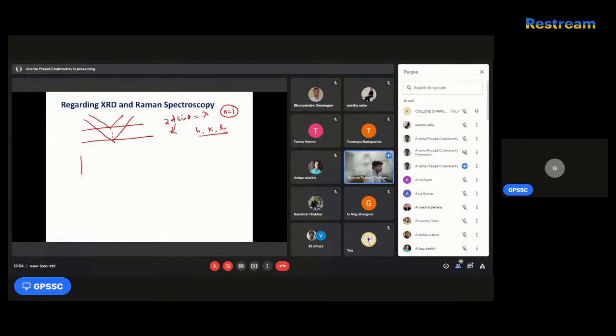So from that you can understand the different crystallographic structures through this XRD, X-ray diffraction, at different 2 theta angles. Generally you have to plot 2 theta with respect to intensity, and you have to take this intensity as arbitrary, because intensity can vary with respect to the machine, but the peak position is specified. So you can see different peaks are coming, and you have to analyze with different software, like the Rietveld analysis, as Marpanda sir has already told. Then you can go for the published XRD files through JCPDS, in the journals. Then you can confirm whether the material you are fabricating already exists, or whether you have fabricated any new kind of material, that also you can visualize.